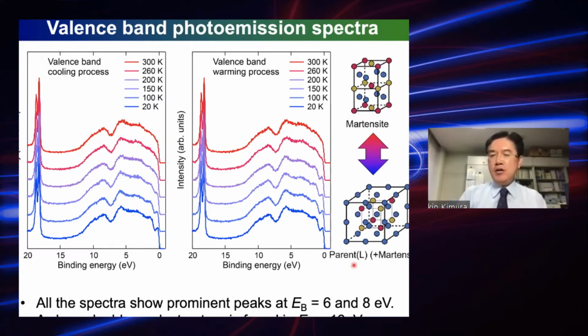So now we see some valence band photoemission spectra. On the left-hand side, I'd like to show you the change of the density of states, starting from 300 Kelvin down to 20 Kelvin. You see almost similar behaviors for all the temperatures, except for something very close to the Fermi energy.